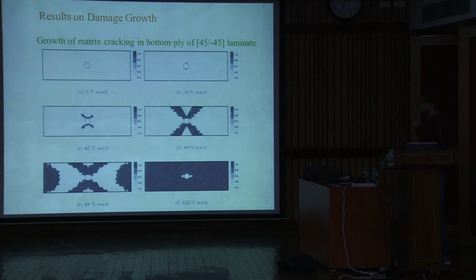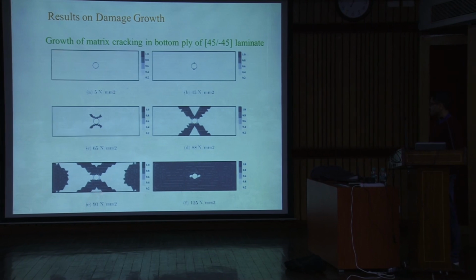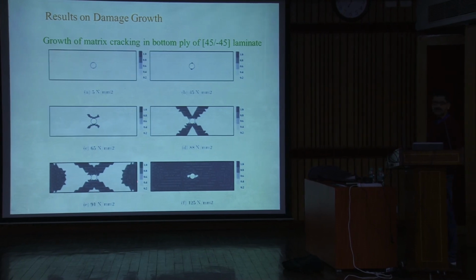So this is another laminate. This is plus minus 45 laminate, and what is shown here is the matrix cracking. Again, the matrix crack starts from this edge of the hole, and as you can see here, it is going in this direction and this direction. So this is nothing but your plus minus 45 fiber direction. So you see that the matrix cracks grow along the fiber line. This is the preferred orientation of this matrix cracking. So it goes, and at a certain stage, it also starts from the edges, and then there is cracking.